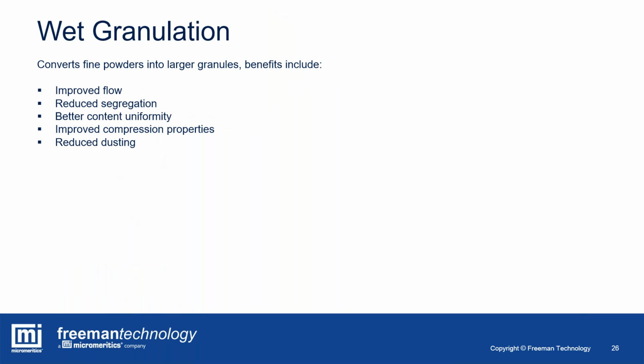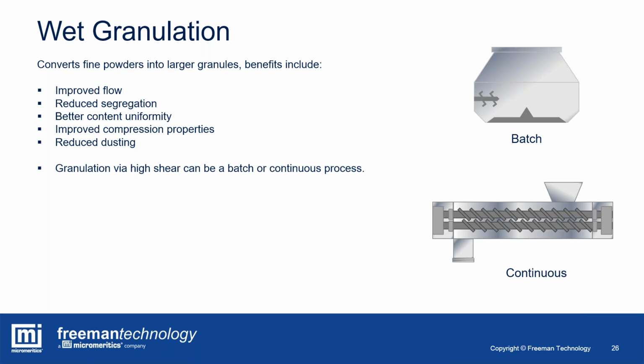For those that are not that familiar with wet granulation, this is a process that converts fine powders, typically with poorer flow properties, into large granules, and the benefit is that you get improved flow, a reduction in segregation potential, that leads to better content uniformity, improved compression properties, and reduced dusting. And granulation via this technique is a high shear process.